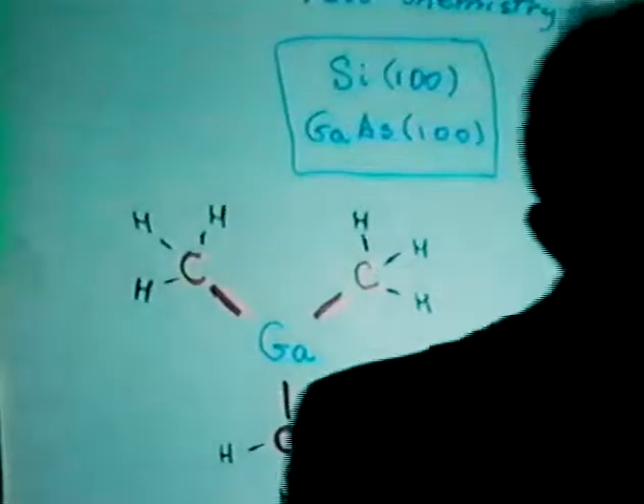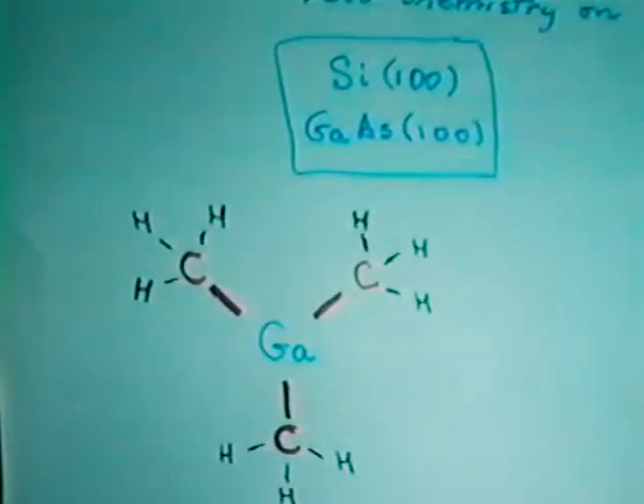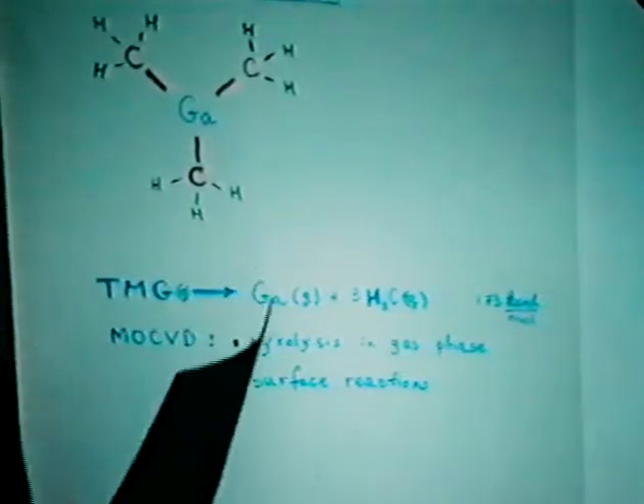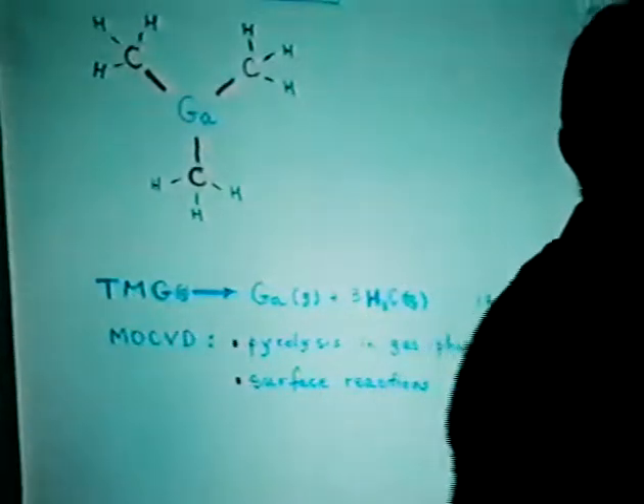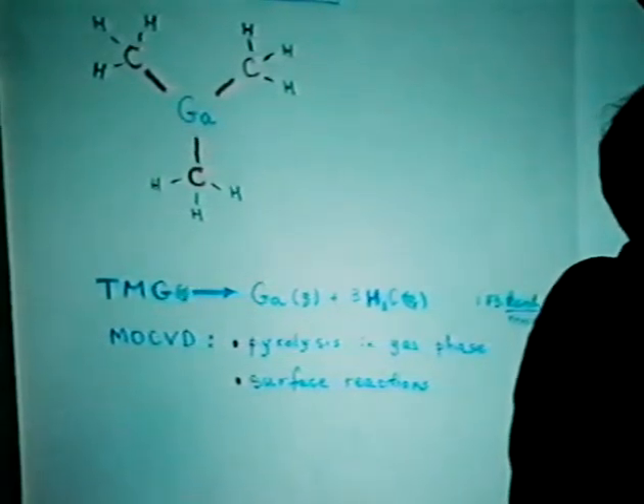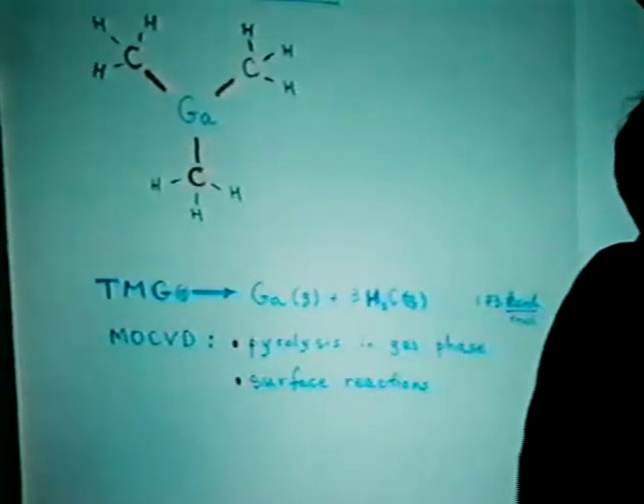So, just to get you oriented a little bit, you would pyrolyze trimethyl gallium in the gas phase into 3 methyl groups and a gallium, and you'd end up with 60 kilocalories per mole as a requirement for what's going on. So I put this in here just to stress that we've got to get more than just surface chemistry involved. We need some really good gas phase chemists involved. In my own group, I can probably handle that problem reasonably well since I was trained there, but that's an important aspect of what's going on in the gas phase.